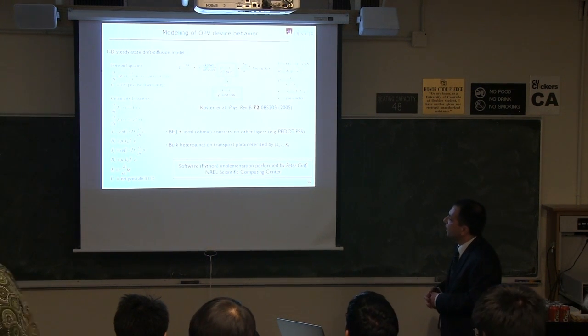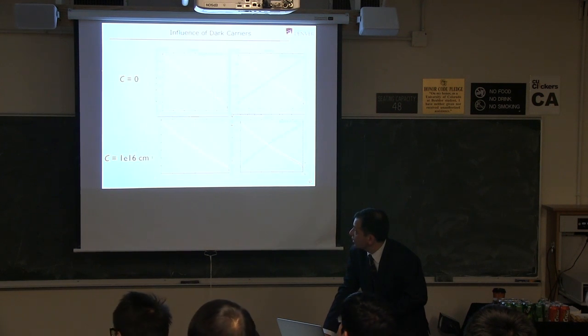The point is that you can use all these equations just fine, the same you would use for an inorganic device, because once the exciton is dissociated, all the rest of the physics is primarily the same. However, to get to the dissociated state, you have to do a kinetic diagram like I discussed, where you have this charge transfer state that acts as a reservoir for the free carriers. So that's included in the model. We've done that, and one thing we've added is that you can put dark carriers in the device. Those are impurity-based carriers that we would like to get rid of, but we know they're in there.